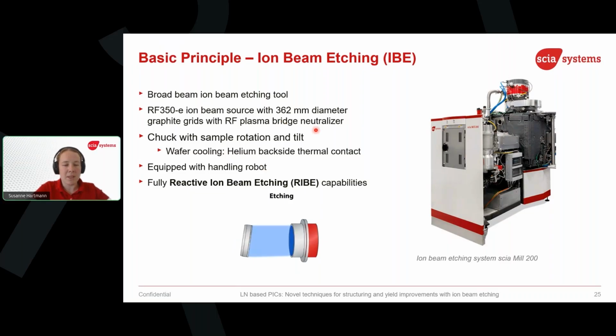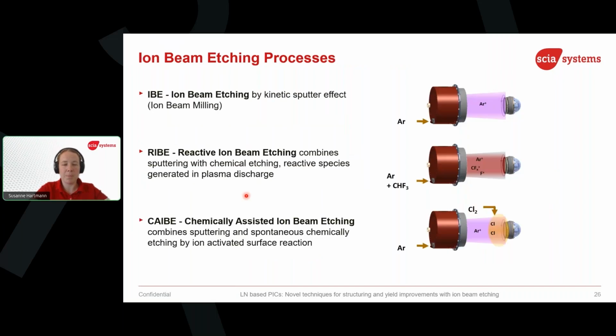The ion beam source itself has a diameter of 362 millimeters, so it is much larger than the 8-inch wafer that can be etched in here. So we have a very uniform etching. Also, for the uniform etching, the wafer is rotated all the time. And not only this, we can also do reactive ion beam etching within this machine. I want to introduce to you this topic a bit further.